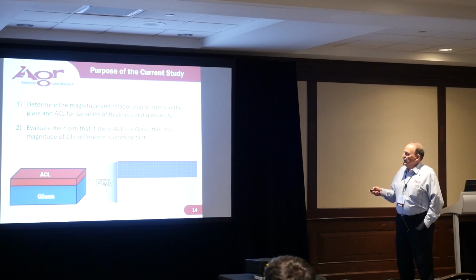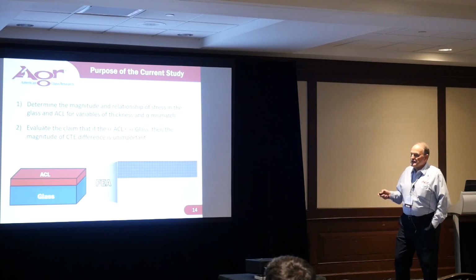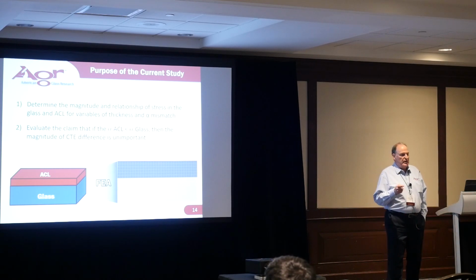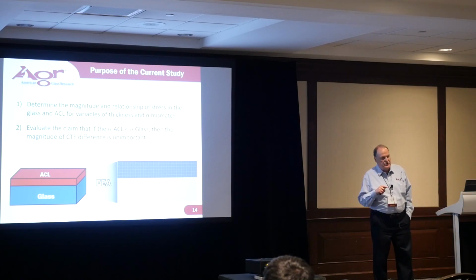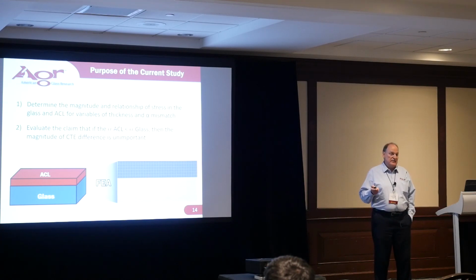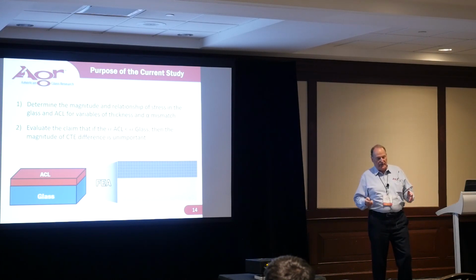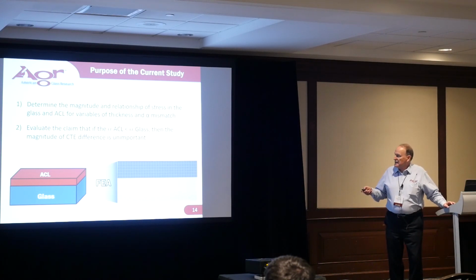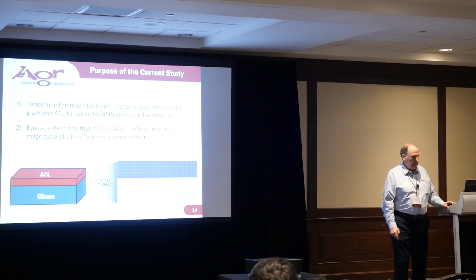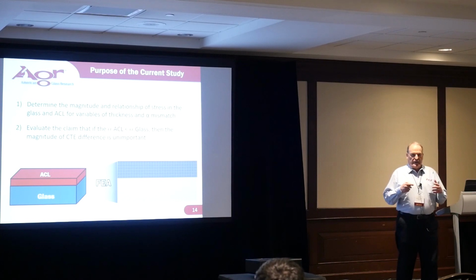First of all, we wanted to find out what is the relationship between the stresses that you can measure in the glass and the stresses that are then present in the ACL. Experimentally, you can't determine it, so we had to do it analytically. And then the second purpose was to evaluate this claim that we found in the published literature that if you have the desired mismatch, the magnitude of the mismatch doesn't matter.